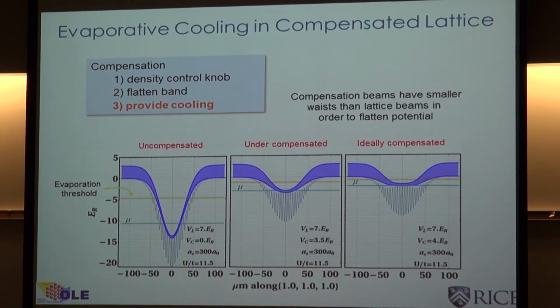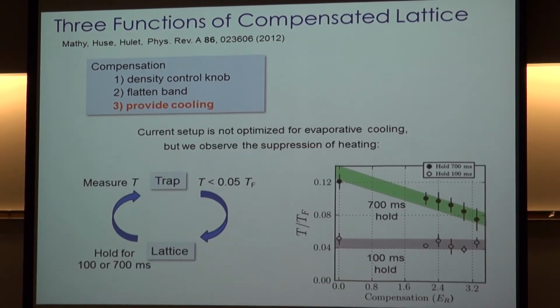And then thirdly, it provides cooling. So here's the chemical potential relative to the evaporation threshold. This is 0 compensation. This is relatively small compensation. This is ideal compensation where we have both a flat band and the chemical potential is very close to the edge. And so by playing with that, you can realize cooling. And that's shown here. So we don't really have a thermometer in the lattice, well we do now, and I'll show that at the end.